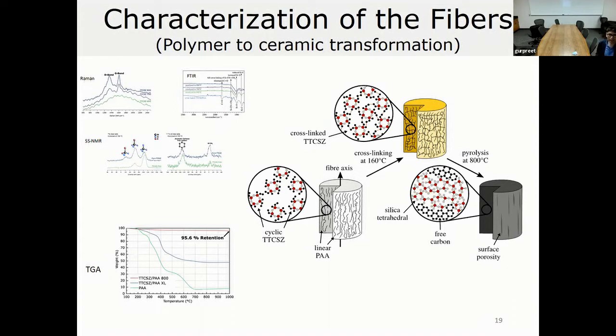We believe that the PAA linear polymer forms a rigid network, and then cyclic siloxane is immobilized in that rigid network. During the cross-linking phase, the pre-ceramic polymer cross-links via the vinyl groups. And then during the pyrolysis stages, the PAA transforms into the free carbon phase, while the siloxane transforms into SiCN.